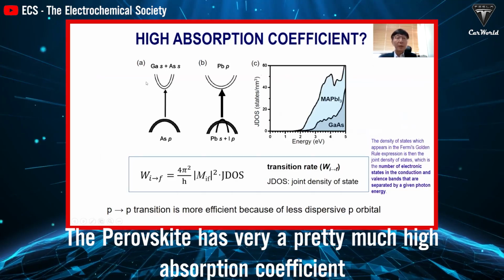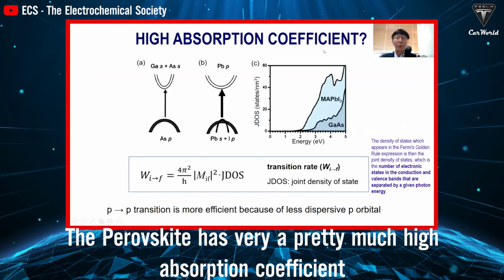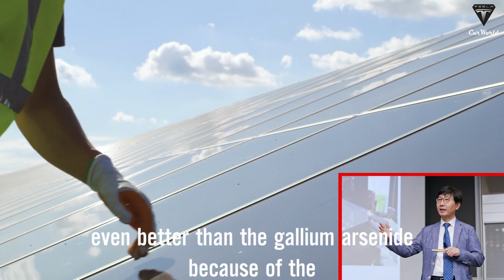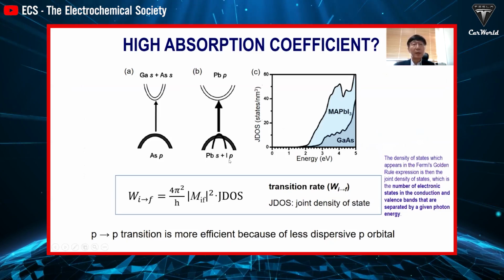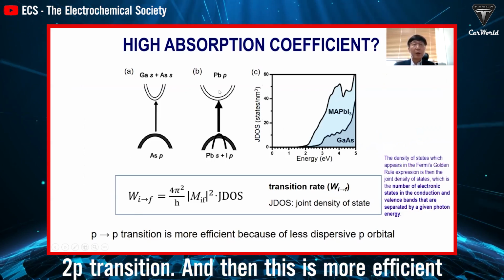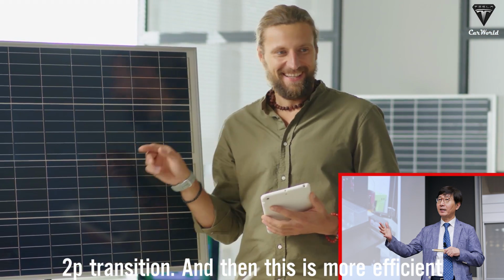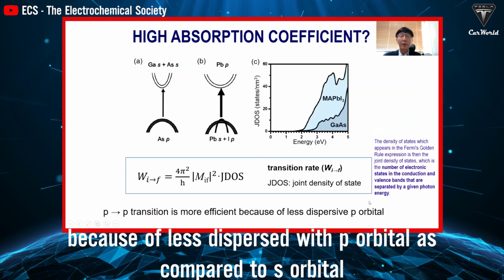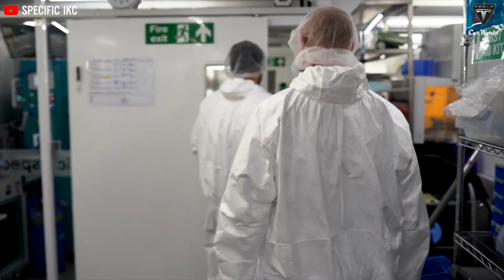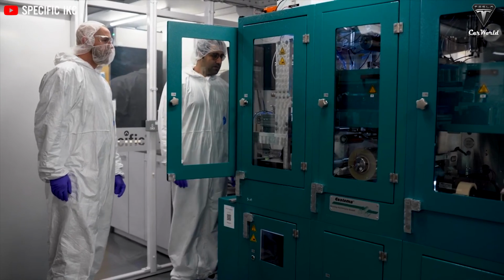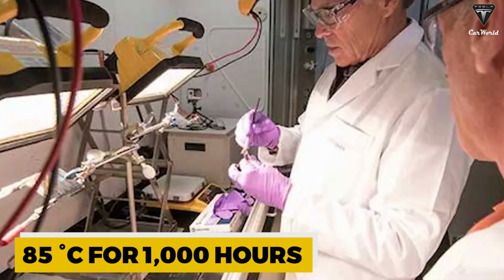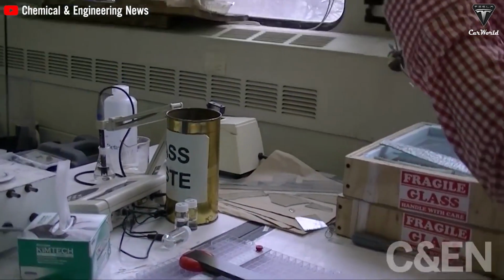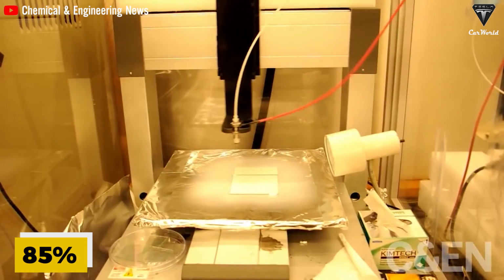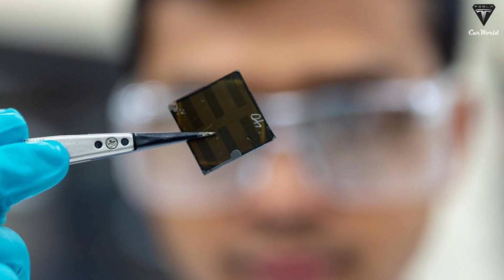Professor Namgyu Park from Sungkyunkwan University said, So the perovskite has a pretty high absorption coefficient, even better than gallium arsenide, because of the p to p transition. And then this is more efficient because of less dispersion with p orbital as compared to s orbital. To better understand, researchers had made tests to measure its efficiency. The perovskite modules are heated up to 85 degrees Celsius for 1,000 hours at a humidity level of 85% and bombarded with hailstones. It passed the tests with unexpected results.